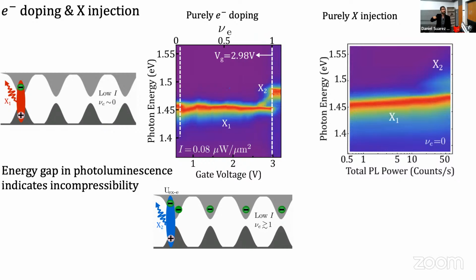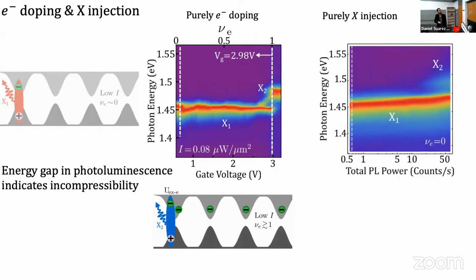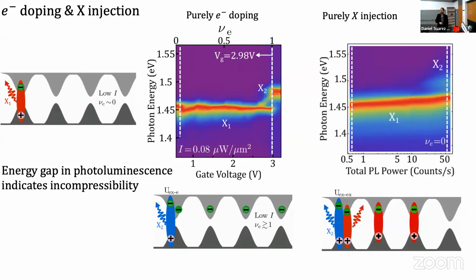But now we can also generate these kinds of states optically, populating our system with bosons. How do we achieve this? Well, we can increase the pump power, and then we monitor the total PL power of the material, which we assume is proportional to the number of excitons in the device. And notice how, as we increase the total PL power, the gap energy again takes place. So what is the situation? We start again from an empty lattice, and as we increase the optical pump, we achieve an excitonic population in the material that strongly interact, achieving the mentioned gap.